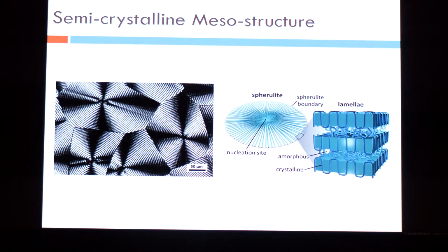Now once you make these products, another interesting set of things come up. All the commodity polymers that I talked about, not all of them, but the polyethylenes and polypropylenes and the PET, they can crystallize. And polymers crystallize in very, very different ways than a low molecular weight species. And because they are these long chains, what happens is as the polymer melt cools down, these long chains start to fold. And they fold and pack into a crystalline lattice. So on the right you will see a chain that is folded and it packs into a crystalline lattice. And when they pack, they form beautiful lamellae, thin films of packed chains.